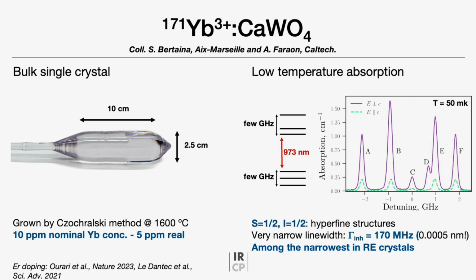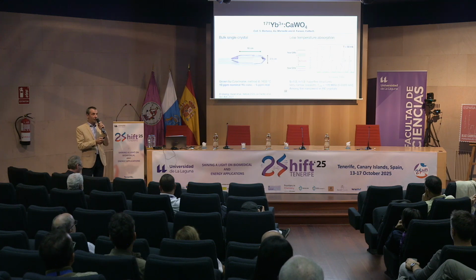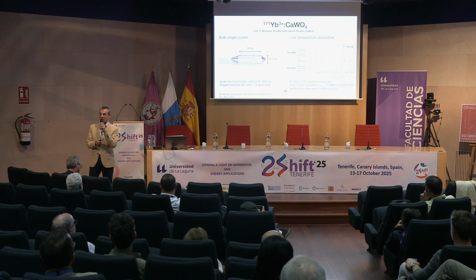And we dope the material with ytterbium. The nominal concentration is 10 ppm, but because of segregation, I would have only 5 ppm really in the material. This was determined by EPR spectroscopy. Why such a low concentration? It's simply because we want to avoid, as much as we can, interactions between ytterbium ions. So of course, with 5 ppm, it's not so much, right? So you may wonder, but really, can you see anything in such a material at such low concentration, only 5 parts per million? Yeah, actually, yes.